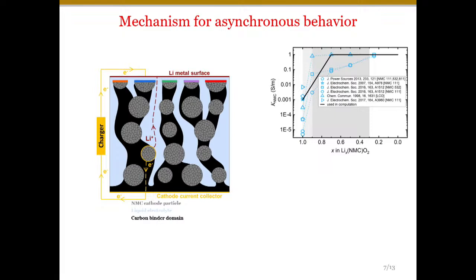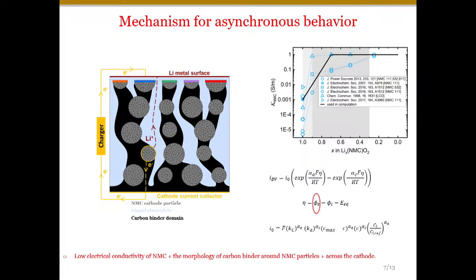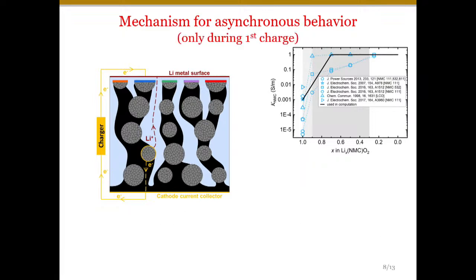This becomes important because inherently NMC, our active material, has around 4 to 5 orders lower electrical conductivity compared to the black carbon binder domain. So that's why even for particles which are nearby, based on the Butler-Volmer relation, we find a lot of variation in phi s, the electric potential. This essentially creates the asynchronous behavior.